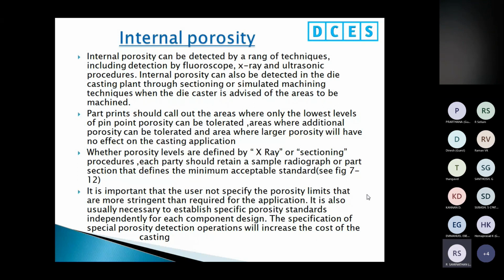Part prints should call out the areas where only the lowest level of pinpoint porosity can be tolerated, areas where additional porosity can be tolerated, and areas where large porosity will have no effect on the casting application. This all should be noted in the drawing itself. Whether porosity levels are defined by X-ray or sectioning procedure, each party should retain the sample radiograph or part section, each party being the die caster and the customer. The part section defines the minimum acceptable standard. I already showed the figure 712.